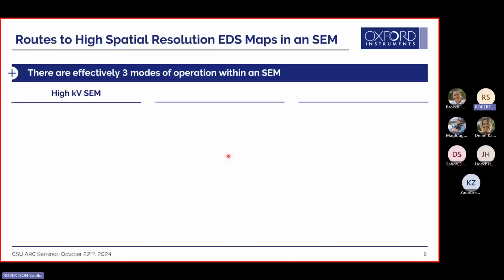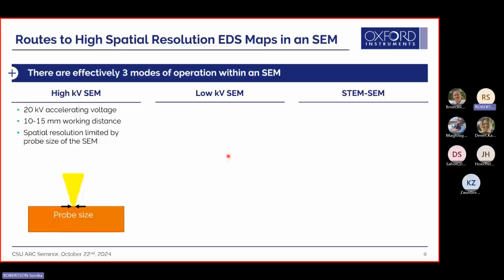Okay. Normal analysis is high kV SEM. This is what you'll call 15, 20 kV. There's the low kV SEM mode, or you could do what's called STEM in SEM. So STEM, but not in your TEM, in an SEM. As I mentioned, this is what we use the most often. In fact, I visited a lab briefly where there was a note behind the SEM saying, do not change the voltage from 20 kV. You don't ever want that. I don't know what those people thought, if it's going to destroy the machine or something, but they weren't realizing that depending on what you're trying to do, you will want to vary the voltage.